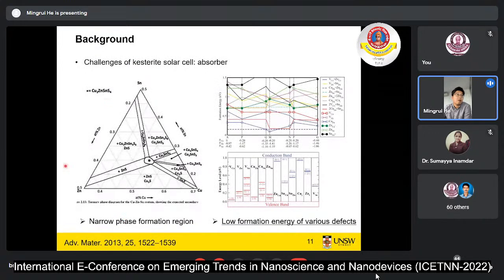As you can see from this diagram, because we want to form the pure CZTS phase, copper 2, zinc, tin, and sulfur 4, it is quite difficult to form this kind of phase. If the composition turns a little bit, we can easily get some second phases, like copper sulfide, zinc sulfide, or some other ternary phases, copper zinc sulfide, copper tin sulfide. This is the first problem we need to take a look at.